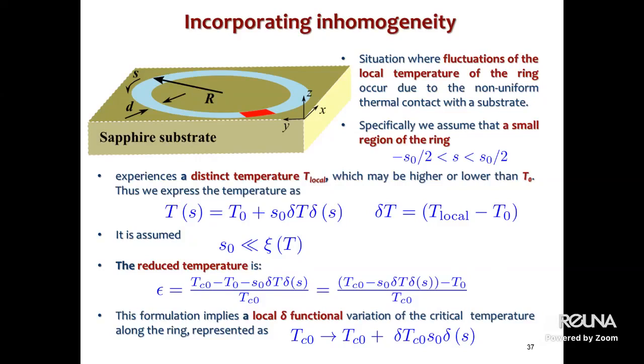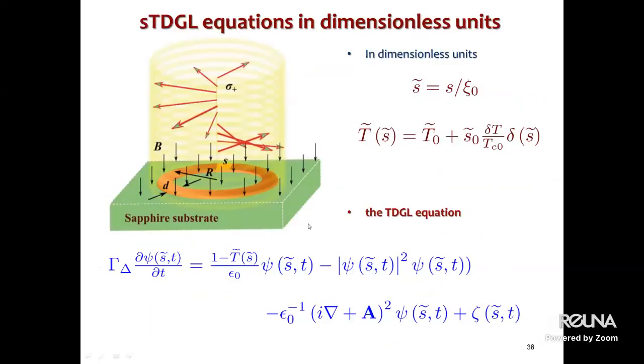The first one can originate, for example, from fluctuations of ring parameters or local defects. The second one is from, for example, a bad contact at some certain point of the ring between the ring and the substrate. Again, for that, we employ the stochastic time-dependent Ginzburg-Landau equation. The local temperature variation is incorporated already through the first term of the equation. So it's here, this local temperature variation.